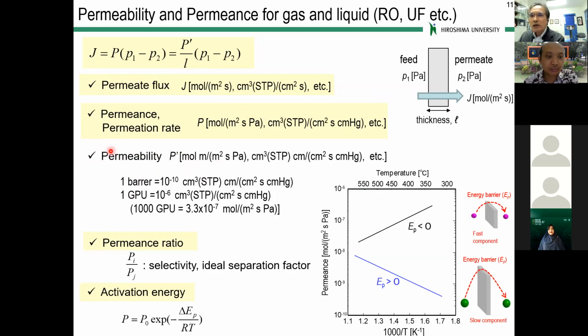But in the case of inorganic membranes, the actual thickness is very difficult to measure. So usually we evaluate membrane performance with permeance in this unit, okay? And this is a dimension conversion. 1 GPU, gas permeation unit, is often used by polymer people. 1000 GPU corresponds to 3.3 × 10⁻⁷ mol per square meter per second per pascal. So if we have 10⁻⁶, that is a high flux, okay? And to evaluate selectivity, the permeance ratio is very important. The permeance ratio of the i component and the j component is often called the permeance ratio or selectivity.